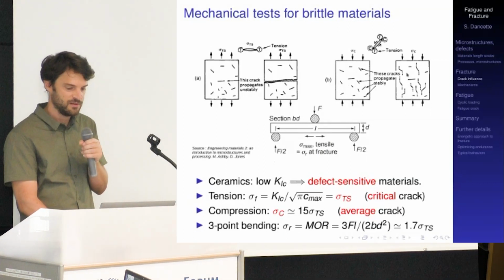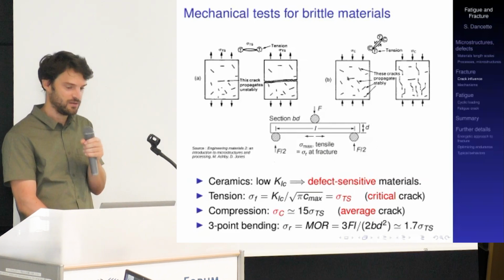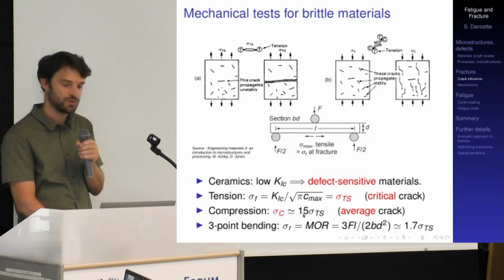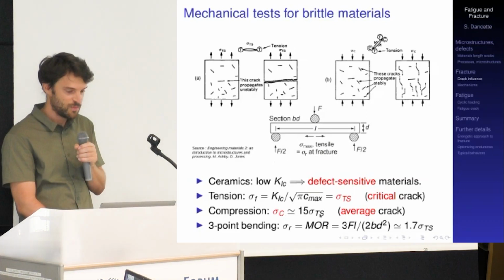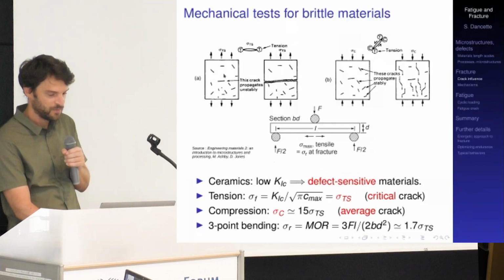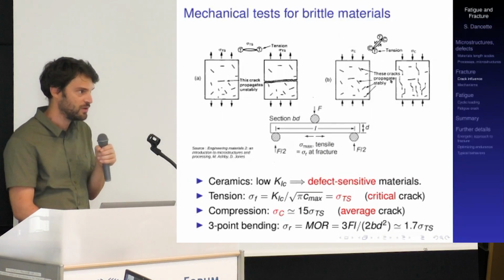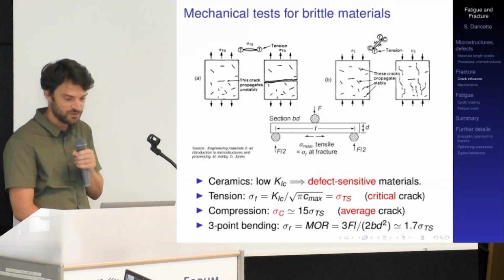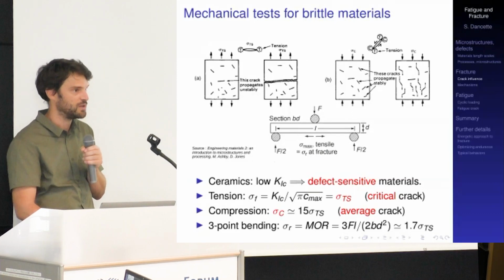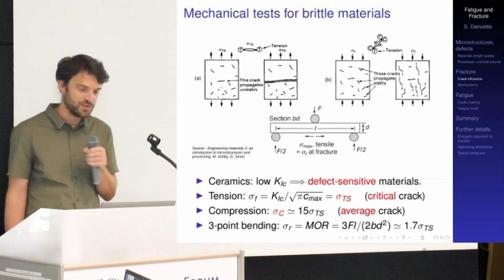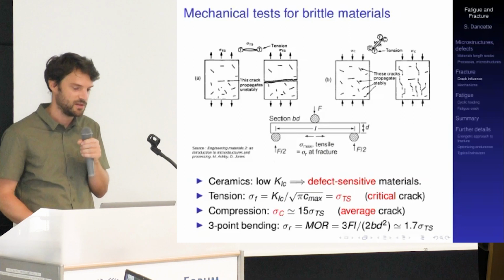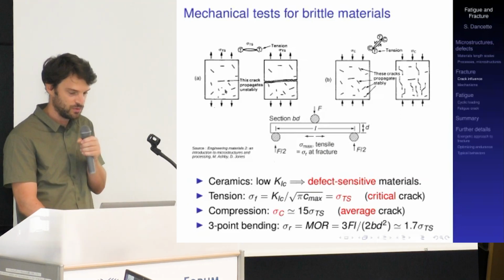And the result of this deviation and stable propagation of the crack in compression is that the fracture stress, usually in brittle materials, might be as high as 15 times bigger in compression compared to tension. So same material, but if you load it in tension, it will have a given fracture stress. If you load it in compression, this fracture stress might be as high as 15 times the fracture stress in tension, just because of the way these defects inside of the material will be either stably propagating or critically propagating in an unstable way in the case of tension.